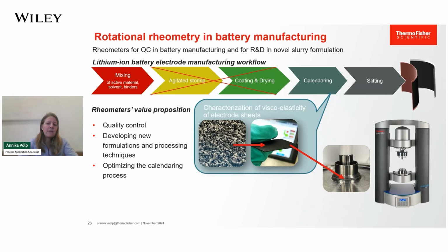The viscoelastic behavior can be tailored using the right binder system and processing parameters in mixing and calendering. Knowing the viscoelasticity of the film, the mixing and calendering steps can be optimized. Certain viscoelastic properties are necessary to yield a homogeneous electrode film, sticking to the calender roll and being then transferred onto the current collector with the second set of rolls. For viscoelastic measurements, the rheometer must be capable of deforming the sample in oscillation.